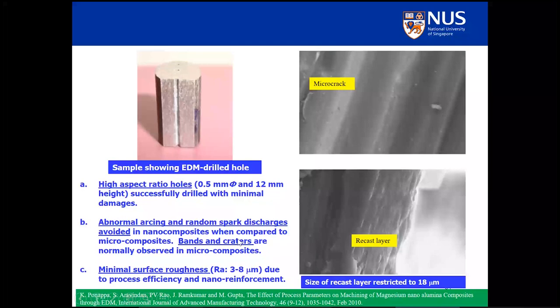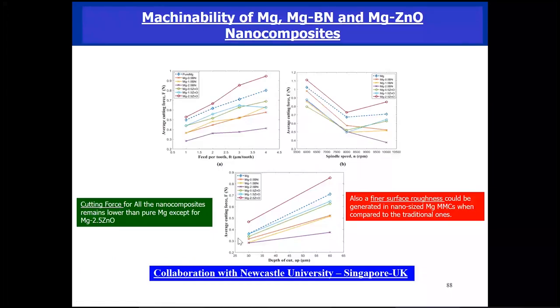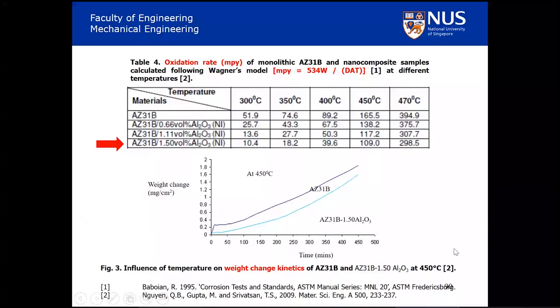Then we gave some more samples about 10 years back to the University of Newcastle in the UK and Singapore, and they found that the cutting forces for all the nanocomposites are smaller except for one exception. That means your machining can be done faster. If your machining can be done faster, your product gets cheaper because you need less manpower, or manpower hours. Now all the materials have to be used in the dry condition or wet condition or both.